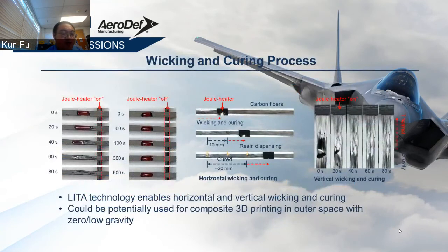All right, so this is our earlier demonstration. As you can see on your left hand, we just use a Joule heater. It's like resistive heating. So we are using this resistive heating as the heater to contact with carbon fiber to provide the thermal gradient. If the Joule heater is on, you can see when we put the resin on the surface, the resin can quickly infiltrate and impregnate into the fiber tows and finally get cured. But if the Joule heater is off, when we deposit the resin, the resin will only stay on the surface. We know that commercial resins have different viscosity, right? They have different